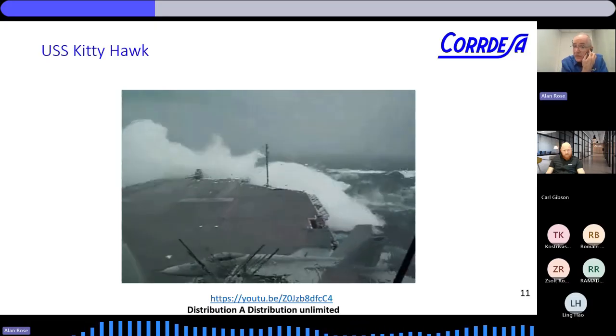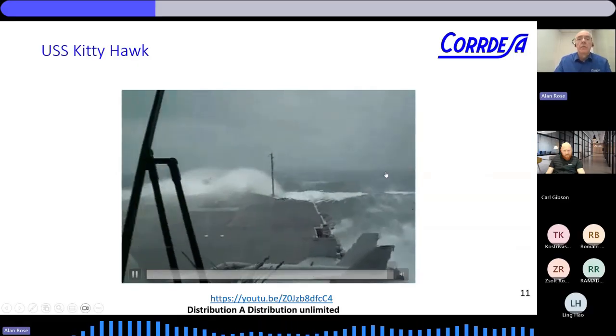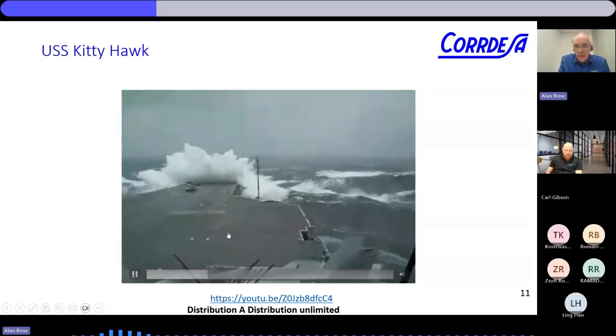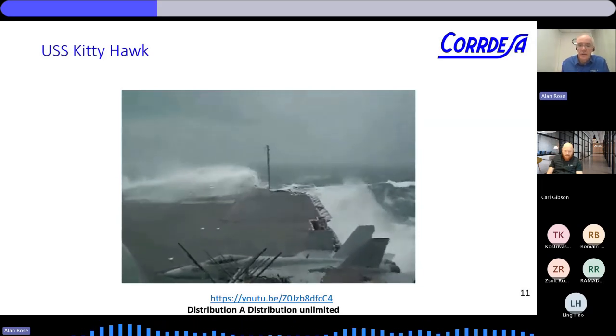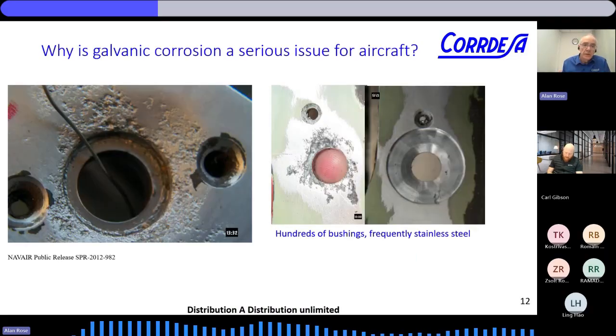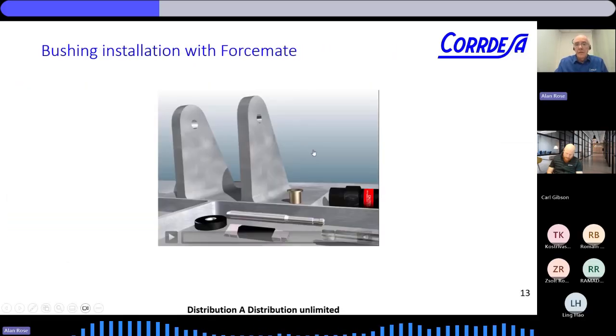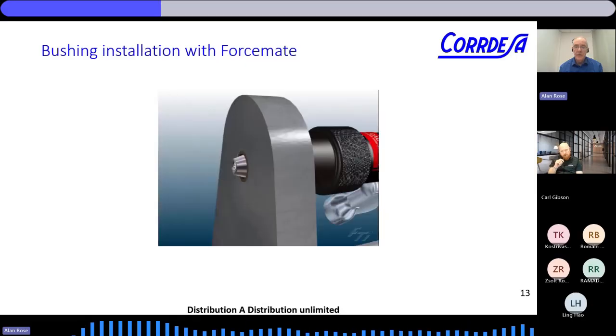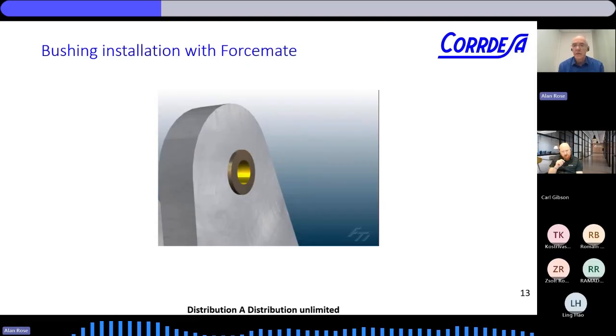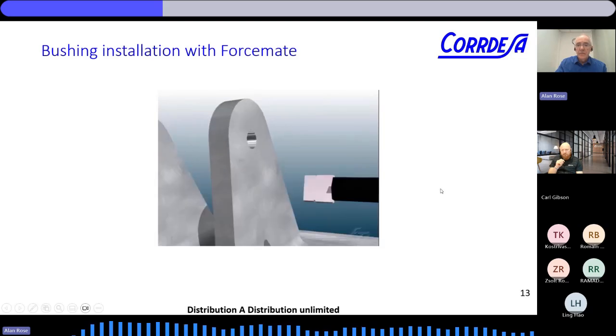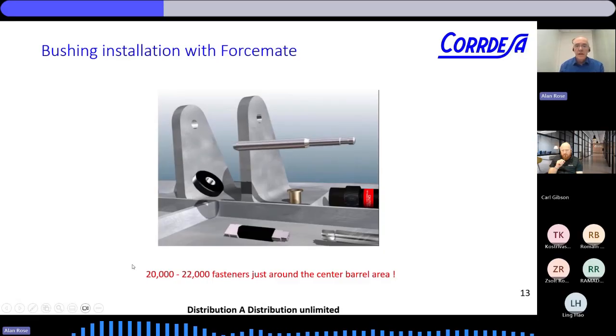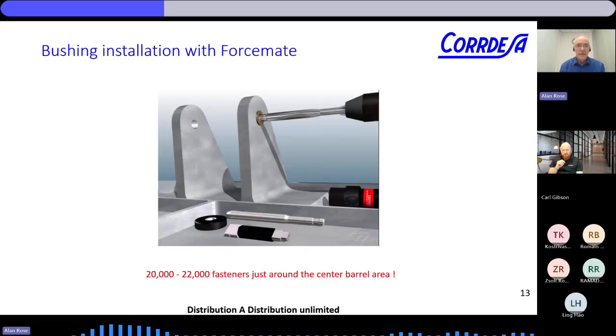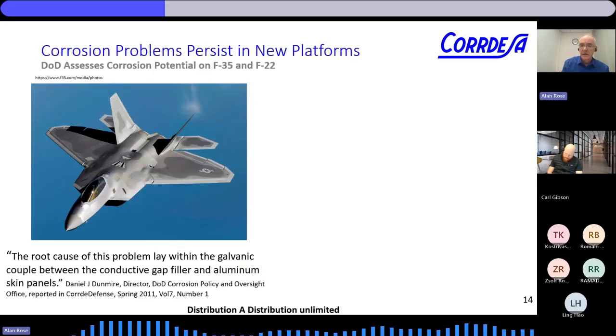And it's not surprising when you look at this, the hostile environments that the Navy had to cope with is kind of mind-boggling, really. They dump tons of seawater onto these helicopters and planes. So looking closely, this is the corrosion that you can get, and the impact is you have to repair it. So what they do is remove the corrosion, and then there's various different ways of putting a bushing in there to bring back that tolerance. They freeze them in liquid nitrogen, or they force mate them in this cold forming process. Either way, it takes labor, it takes time. And when you consider that there are more than 20,000 fasteners in the center barrel of an F-18, that could be a very expensive process.